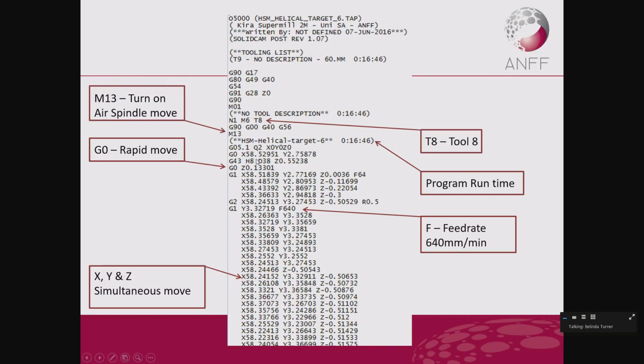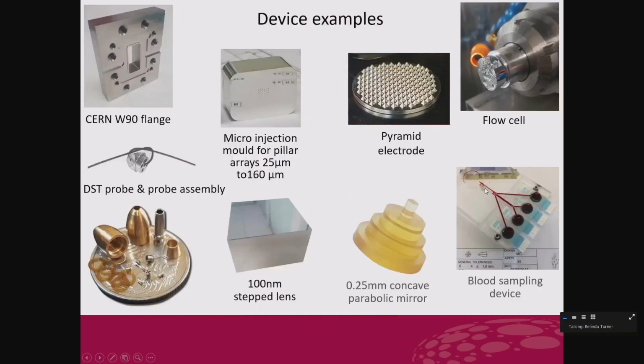And some of these are machine functions, but a lot of the time it's just X, Y, Z positions, and then a feed rate maybe. But you can see the level we've gone to on here, where we're going down to 10 nanometers, whether it's truly at that position. Just like I said, the machine's 10 nanometers, and we're trying to achieve a micron sort of accuracy on the parts we make, which I'll go into in a second.